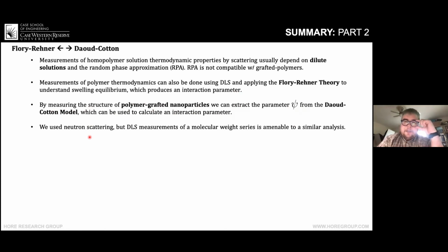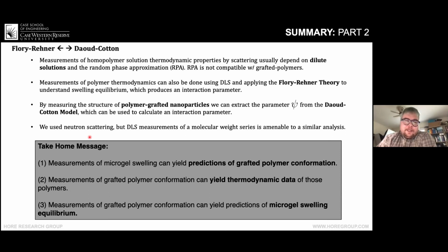So in the event that you have something that you can't gel, if it's impossible to get a microgel for your particular polymer, then if you can measure the polymer grafted nanoparticle conformation, then you can get the parameters that describe its thermodynamic behavior. So the take-home message I'd like to leave you with today is that measurements of microgel swelling can yield predictions of the grafted polymer conformation, but also the measurement of grafted polymer conformation can yield the thermodynamic data. And finally, what I really enjoy about this work is that if you measure the polymer grafted nanoparticles and you measure the conformation of the chains, you can get predictions of how microgels will swell.